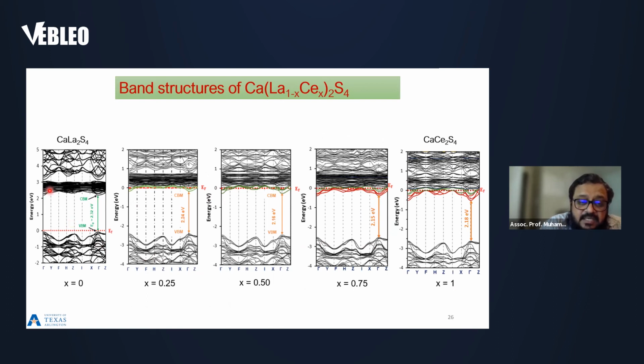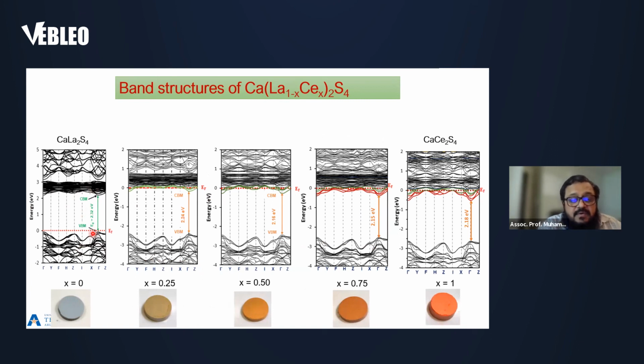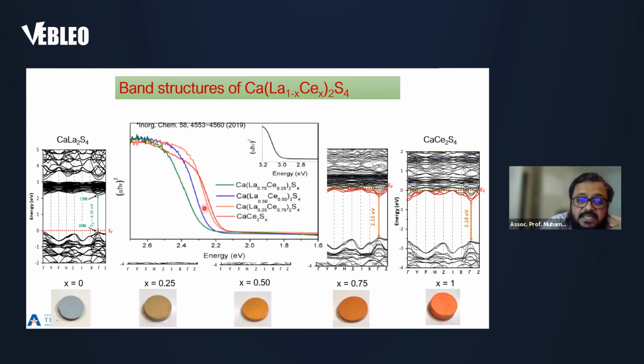Again, as we mentioned, this band gap is highly underestimated based on the color of the sample. This kind of whitish sample color means the band gap or optical gap should be above 3 electron volt. We get a highly underestimated gap. On the other hand, when cerium starts coming in, we compared the gap with the trend of the optical gap or absorption measurement. The trend is maintained. So this one is for calcium lanthanum sulfide.